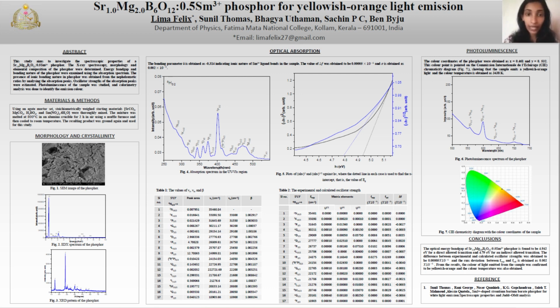Table 1 shows the values of μZ, μA, and β for each transition as well as the area of each peak. Out of the total 17 peaks, 16 of them have β greater than 1, which results in the averaging of β to estimate β dash. β dash is the average value of β, and delta means the bonding parameter. Thus, the bonding parameter is obtained as minus 0.314, indicating the ionic nature of Sm3+ ligand bonds in the sample.